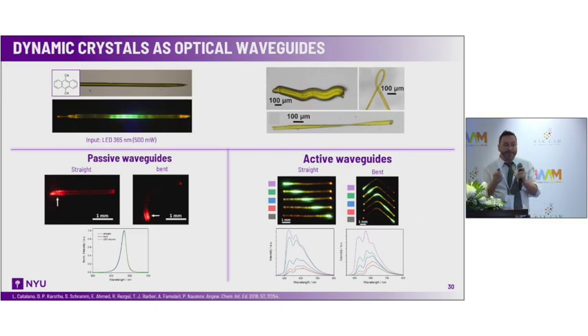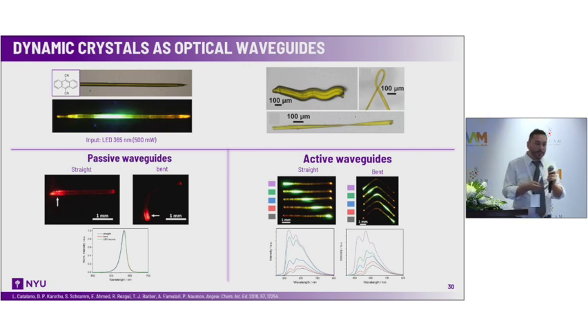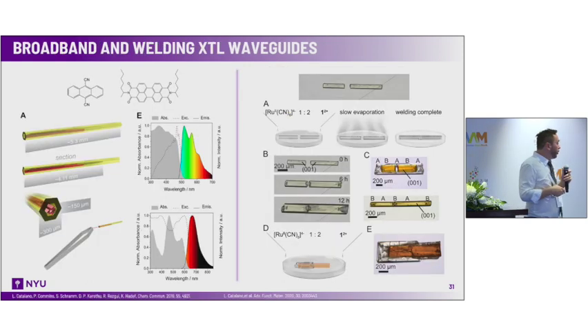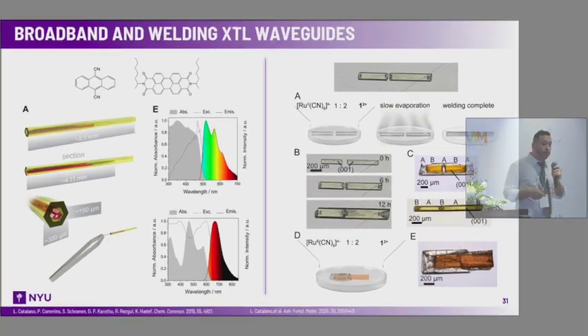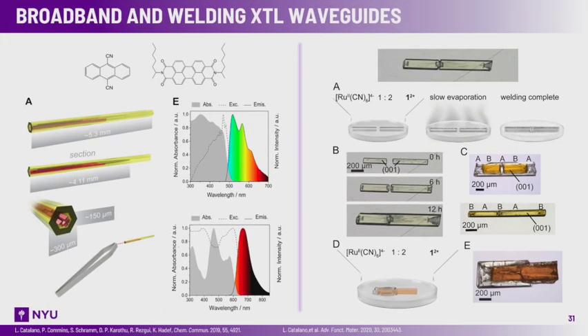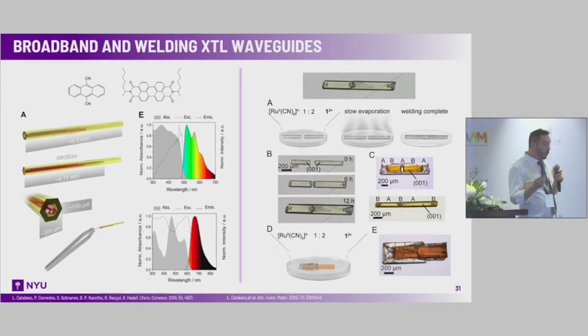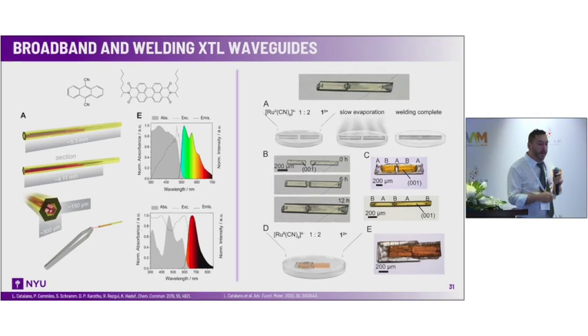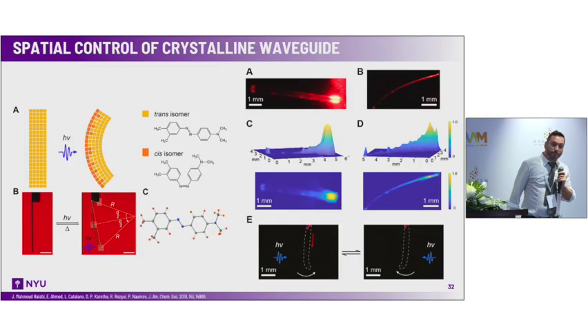For example, you can bend the crystal and make some kind of deformed optical waveguides. You can put crystals inside the crystals and make some sort of hybrid materials. And also you can use epitaxial growth to connect a broken crystal, and so weld it if it was broken. Perhaps this is a very interesting laboratory exercise, but in principle it shows that things that you cannot do with other soft materials can be done by using crystals.